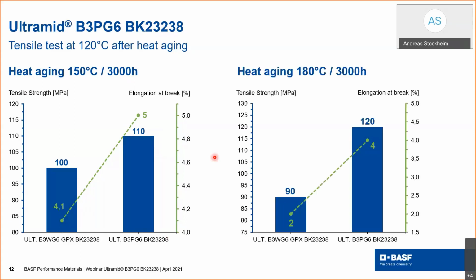The difference to the reference grade becomes even more clear and visible at elevated temperature when we look at heat aging at 180 degrees C after 3,000 hours. So here the tensile strength is 33% higher than the GPX and 100% more in elongation at break.